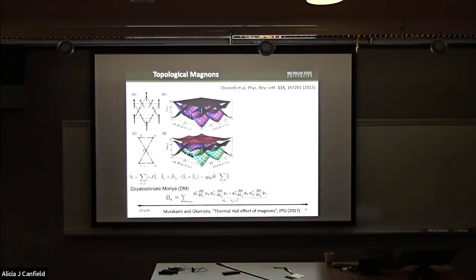For instance, let's say that we have a ferromagnetic Kagome system with the spins pointing up. Because of the Kagome geometry, there are two dispersive bands crossing each other, and a flat band. Since this system has the Kagome lattice, the inversion symmetry is broken relative to the center of the nearest-neighbor bond. Therefore, the DM interaction is allowed. In this case, these two dispersive bands will open a gap at the K point.